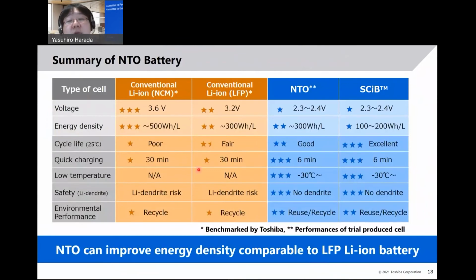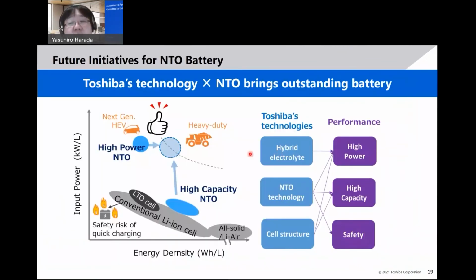This table shows a summary of NTO battery features compared with other chemistry batteries. As you can see here, the NTO battery can achieve almost the same energy density as lithium iron phosphate, the so-called LFP type lithium-ion battery, and has many attractive advantages as well as our SCIB, as shown here. So we believe that a combination of Toshiba's technology and NTO will bring an outstanding battery and make the impossible possible for the electrified society. We have lots of battery-related technologies, not only materials, but also computational technique and so on. So please look forward to our new battery using niobium-based material.